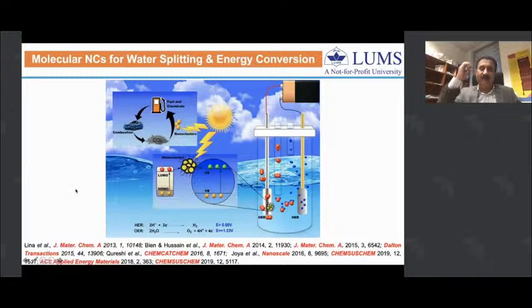Apart from this, very recently we got more interested in transition metal oxide nanoclusters. Nanoclusters, I mean, are nanoparticles smaller than 2 nanometers, and we explore their applications in, for example, water splitting for hydrogen production. We know that water can be split to produce hydrogen gas, but unfortunately the energy input in this case is more than the energy you will get from the produced hydrogen.